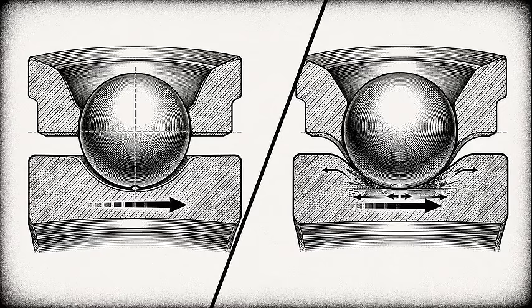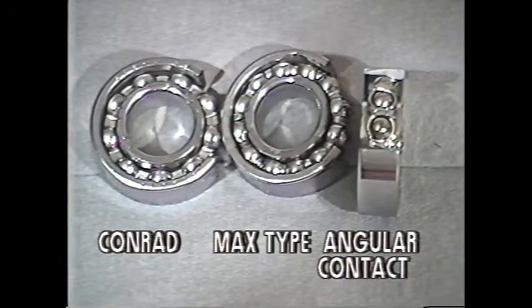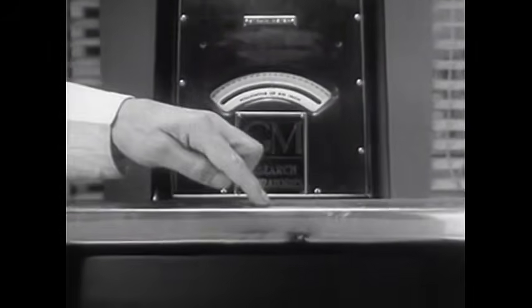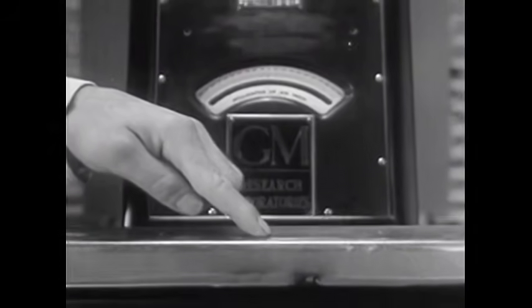So most of the contact band would have to slide rather than roll, which reintroduces exactly the sliding friction the bearing exists to eliminate, generating heat and wear, and destroying the bearing's whole purpose. So the groove is deliberately made a little larger in radius than the ball, conventionally a modest percentage larger, which shrinks the contact back down to something very close to a point. That restores true rolling. But it also concentrates the load into a tiny ellipse, which drives the contact pressure up and demands the hardness and the metallurgical cleanliness discussed earlier. The groove radius is therefore a compromise between friction and stress, and where a manufacturer sets it is a matter of judgment, backed by testing, another piece of proprietary process knowledge.